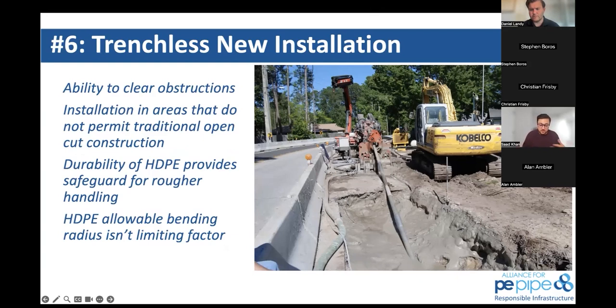So with trenchless, there's two main ways that we see it being utilized in the polyethylene world, and that's HDD, which is horizontal directional drilling, and pipe bursting. So horizontal directional drilling, as the word says, is really installing a new pipeline within an environment within which you can horizontally directionally drill. So you have a laydown yard, you're fusing the pipe. As you're fusing it, a hydraulic winch is actually pulling the pipe into the ground where it needs to be placed.